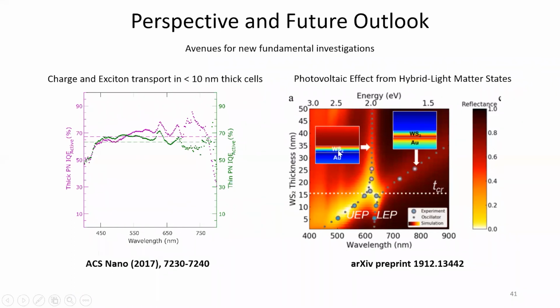I'll also say that we are now working on looking at hybrid light matter states such as exciton polaritons. And I did not talk about this further, but in our structures of WS2 and WSe2 on gold itself, you already see exciton polaritons form at thicknesses even below 15 nanometers, which is where this optimal absorption was. And so now we are trying to see, if you do a photovoltaic measurement, what kind of efficiencies or external quantum efficiencies you can get from an exciton polariton peak versus just an exciton peak, and does it have any fundamental consequences in terms of light harvesting? So there are a lot of interesting things to do over there in the coming years.